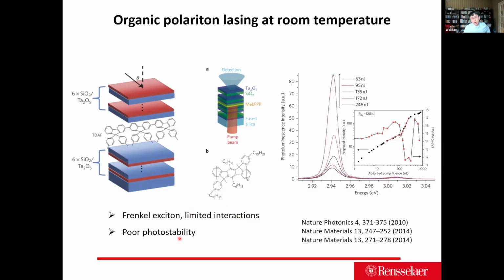Plus, as I said, these are organic molecules. You need to pump it really, really hard to see this condensate in a small region. And soon after this, you start to see degradation because of the intrinsically poor photostability of these organic molecules.